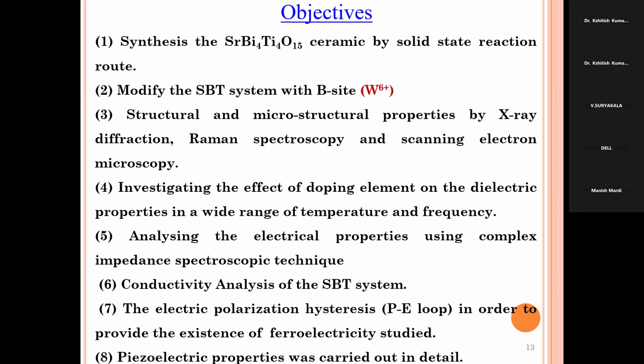Coming to the different characterizations, we first conducted the structural characterization. Then we conducted the electrical characterization, and also the P-E loop, to see whether it is showing a ferroelectric material or not, and what the saturation polarization, the remnant polarization and the coercivity are. For that we conducted the P-E loop. And as it is a high temperature material and the piezoelectric constant is also good, we measured the piezoelectric response not only at room temperature but also at high temperature. That tells us the thermal stability of the material.